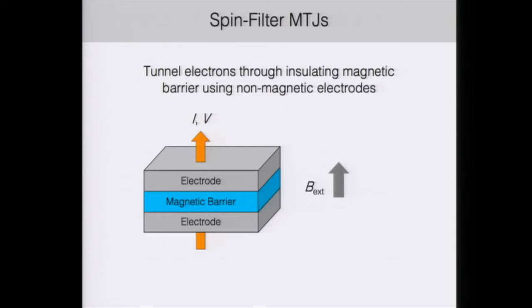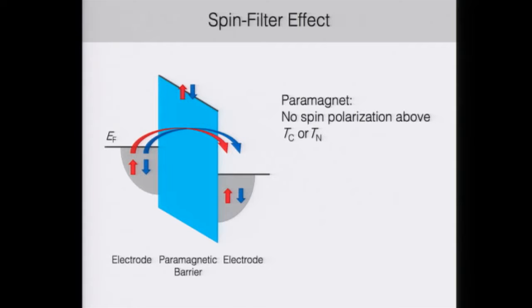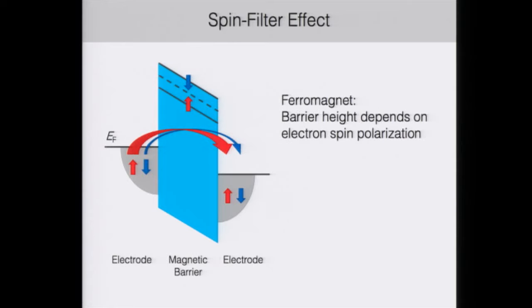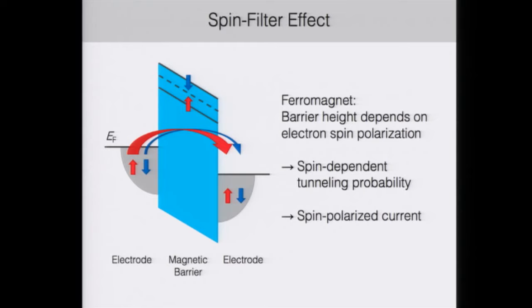In spin filter magnetic tunnel junctions, you tunnel electrons through the magnetic barrier as a function of magnetic field, and then measure the current and voltage response. This underlying effect is called the spin filter effect. So if you imagine having a paramagnet as your barrier and you send in a non-spin polarized electrical current, then since the spin up and down electrons have the same tunnel barrier height, you'll have no spin polarization above the Curie-Néel temperature. If you then cool down below the magnetic ordering temperature, then if you have a ferromagnet, the spin up and spin down bands will be split in energy. And then the barrier height depends on the electron spin polarization. Since there's a spin-dependent tunneling probability, you'll end up with a spin-polarized current on the other side. And so you'll preferentially end up with spin-up electrons in this case compared to spin-down electrons.